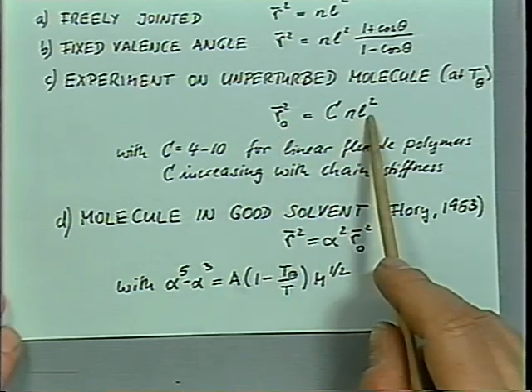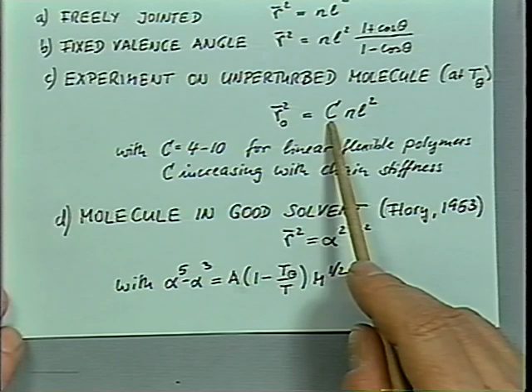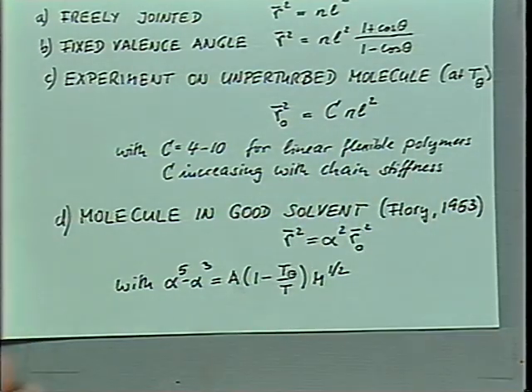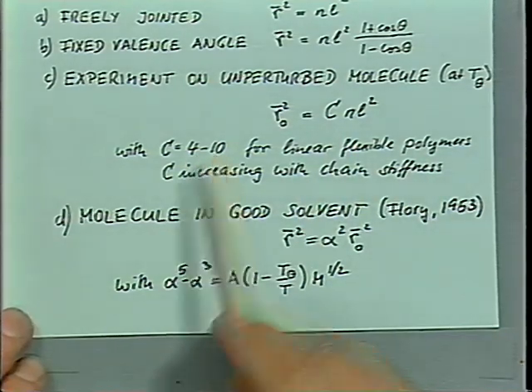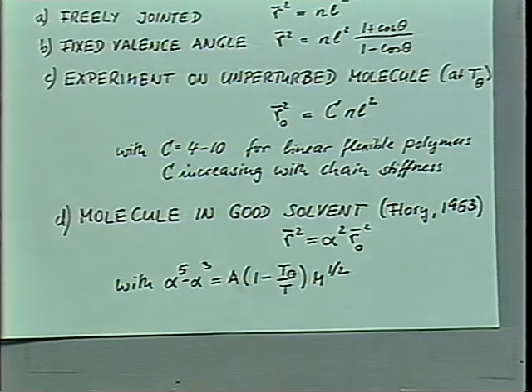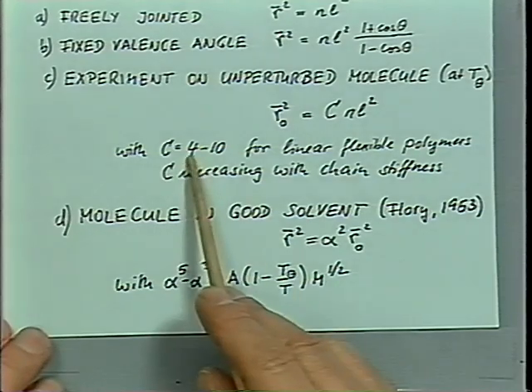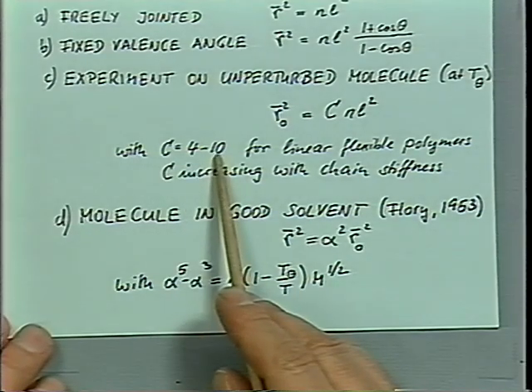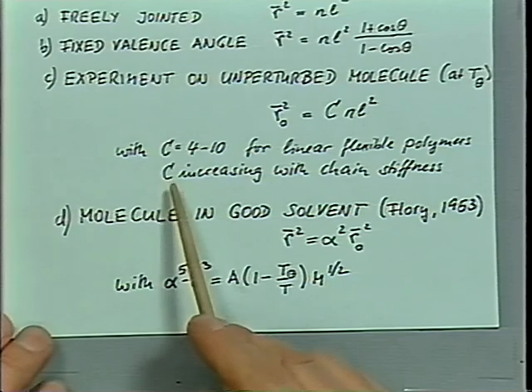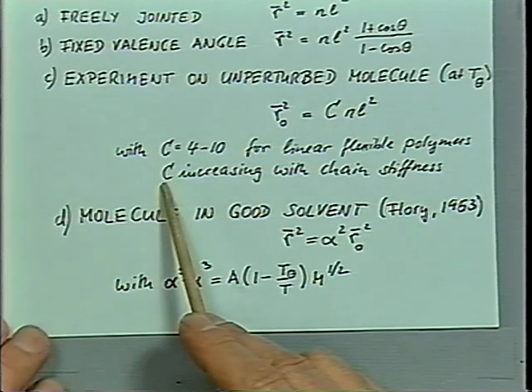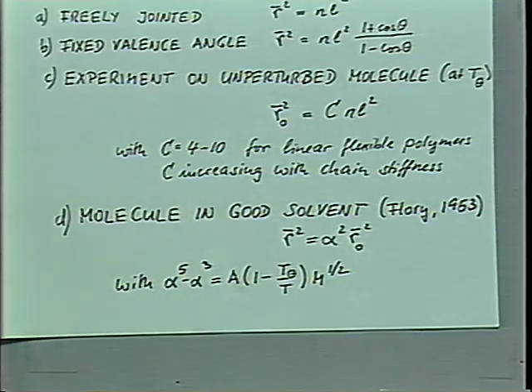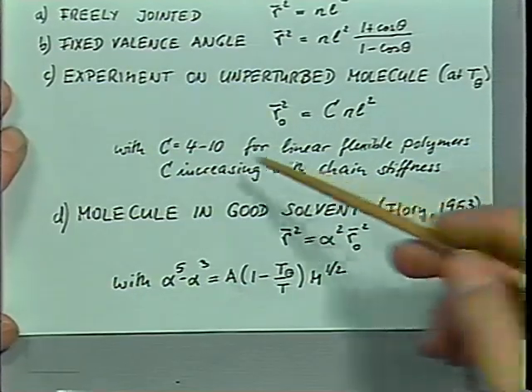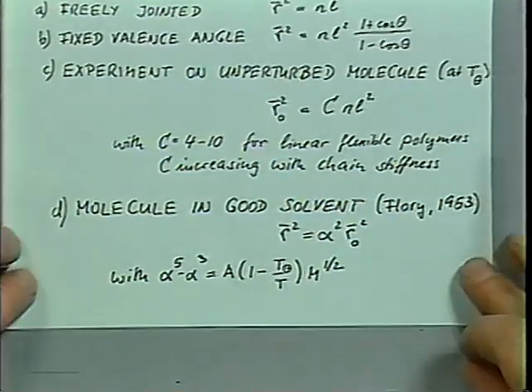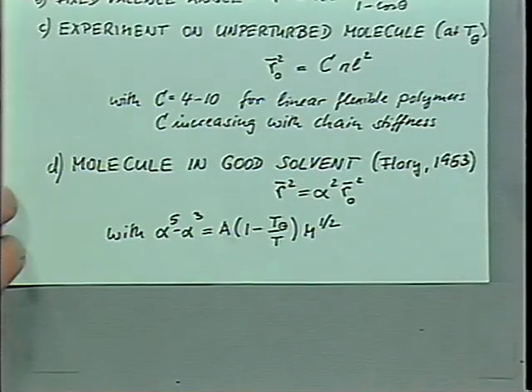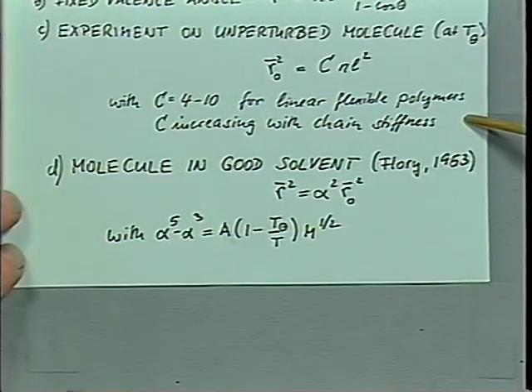Again, it is n l squared with a front factor. And this front factor, C, for most linear molecules is on the order of 4 to 10. And if you are stiffening the chain, if you're not talking about complete flexibility, this factor would be increasing. So in light scattering, this factor is a measure of the flexibility of your coils. We're talking about very flexible polymers where this type of value can be seen. Now, this is in a theta solvent.